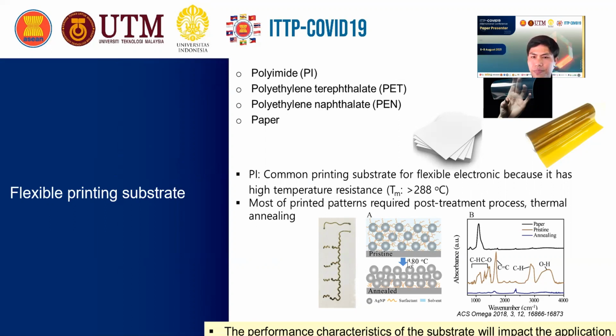We can look at this figure. Material ink is actually a combination of the nanomaterial and some kind of surfactant that attaches on the surface of the particle in order to make the material ink disperse in the solvent. But after printing, those polymers, for example, will inhibit the connection between the particles. So that's why we need high temperature to remove the polymer as gas and make the particles connected together. So that's one thing that we need higher temperature for.